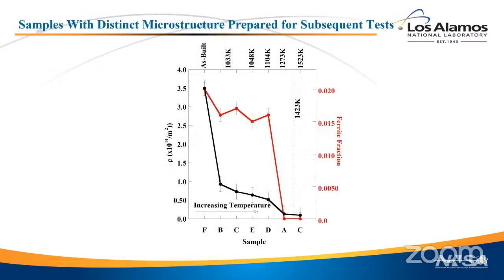Well, if you plot some of those features up, here you see the ferrite fraction in red as a function of temperature as you go through the 6 samples, and the dislocation density as a function of temperature in black. And I did say it backwards earlier. What you see is at lower temperatures, the dislocation density goes away. The ferrite fraction persists to higher temperatures.